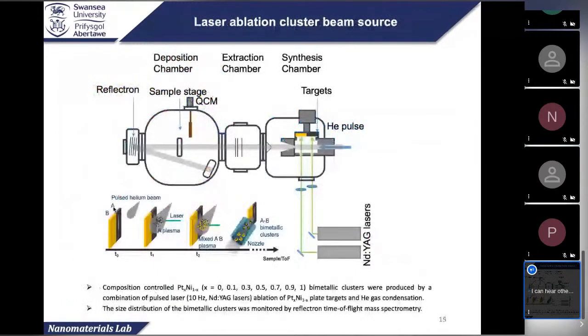And this is the other source we use to produce nanoparticles, which is called a laser ablation cluster beam source. It's quite simple. Instead of using magnetron sputtering, you use a laser to hit the target. You have your target, which can be a single metal or an alloy. You just hit it, and then you generate atoms in the chamber. Meanwhile, we introduce helium as well, so there's a condensation process.